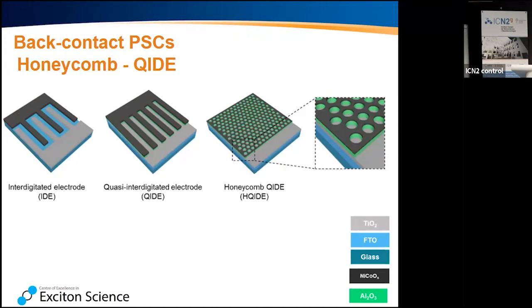A structure that is much more defect tolerant is the so-called honeycomb structure, as we refer to it. Imagine that you have a sandwich with your electron collecting electrode, insulator, and hole collecting electrode, and now you're drilling holes into that material and exposing the electrode underneath. That's pretty much what we have here. It's like having a grid of an insulator and then a grid of a metal collector on top. So if you create charge carriers anywhere, they can either go to the top electrode or find the bottom electrode in their vicinity.